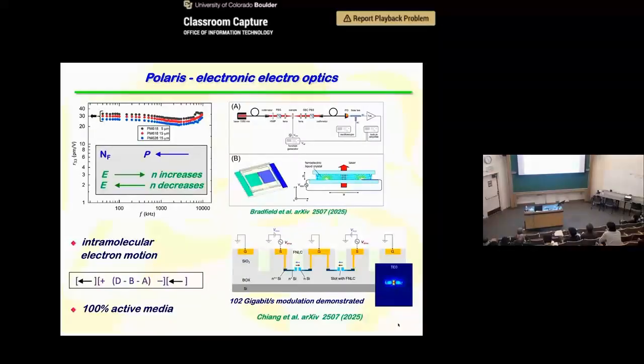But now recently they've been able to make chromophoric molecules that are also ferroelectric nematics. So you can have 100% sort of active medium in the volume that you're using to do phase modulation. So